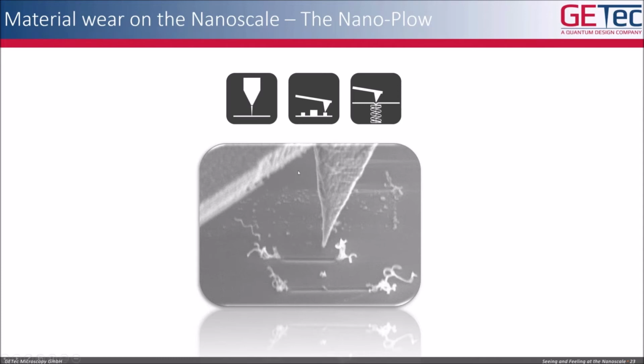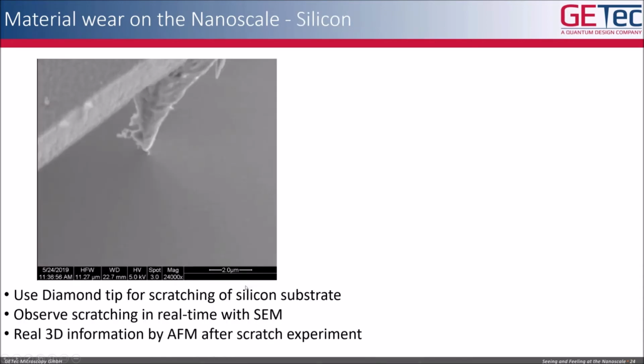Here you see an image of a diamond tip on top of a silicon substrate. And what we tried is, can we use the AFM cantilever with the diamond tip to modify the silicon surface, which is also a quite hard surface.